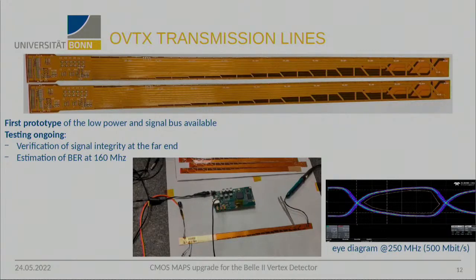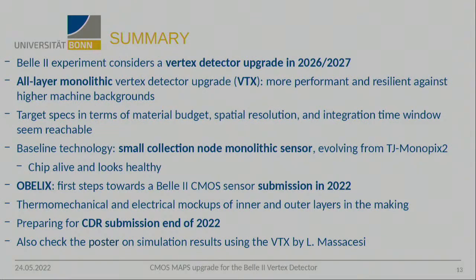To conclude: the Belle 2 experiment considers a Vertex Detector upgrade in 4, 5, 6 years from now. We are planning to build an all-layer monolithic pixel Vertex Detector, which is more performant and more resilient against backgrounds, reducing background hits from 99%, 99.9% on the innermost layers to maybe 30-50% because of the fast integration time. The target specs in terms of material budget, spatial resolution, and time windows seem reachable with derivatives of TJ Monopix.